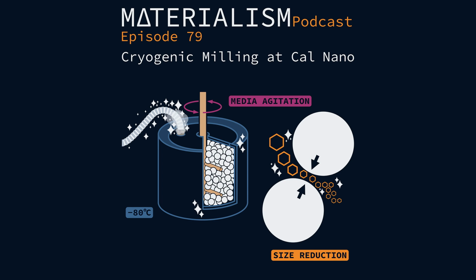I remember my first exposure to this, I was trying to make magnesium silicide from magnesium metal, which turns out will catch fire, right? Especially when it's very small particle size, ignorant me, not knowing this, and silicon. When we tried to mill this stuff together, first off, it got so hot in there that when we opened it, it did cause a small fire. Thank heavens we were dealing with very small amounts, because it actually oxidized spontaneously. But the other problem we found out is that it wasn't even actually forming the compound we wanted, because the magnesium is a super ductile metal and it was accumulating in the corners of our planetary ball mill. And it wasn't actually even forming the compound we wanted, which was really frustrating.